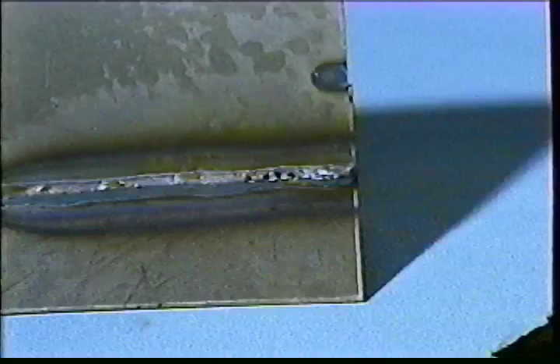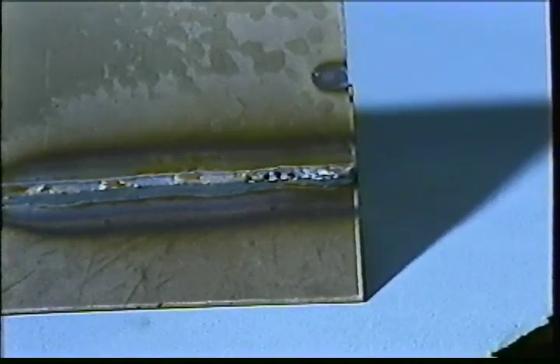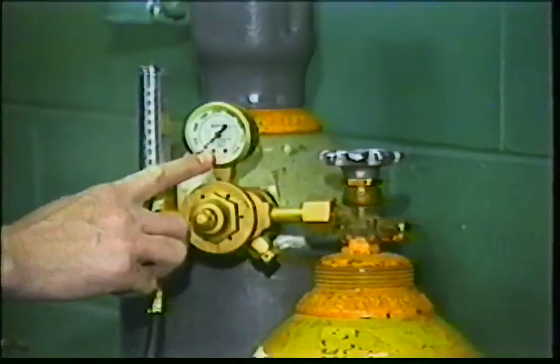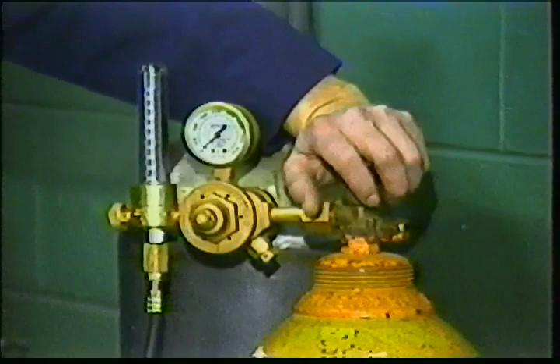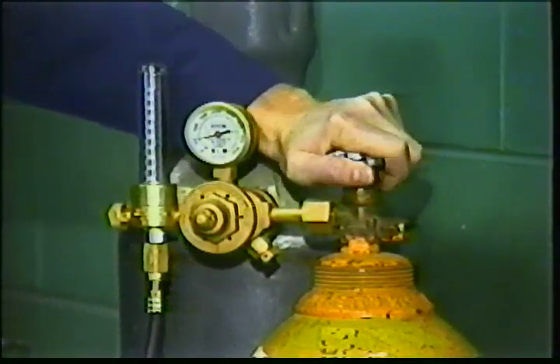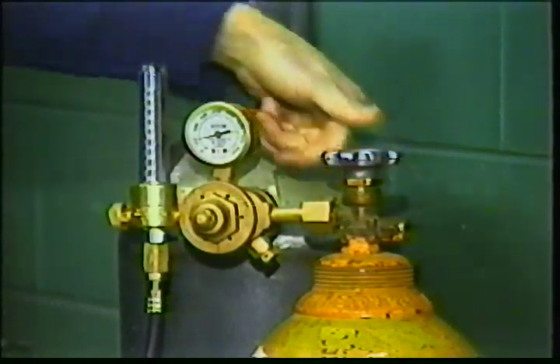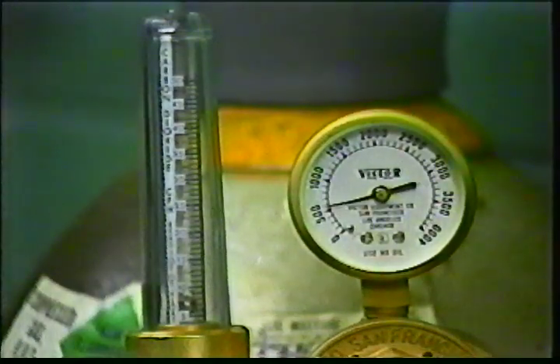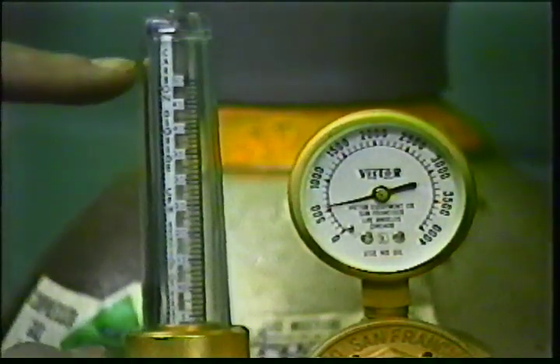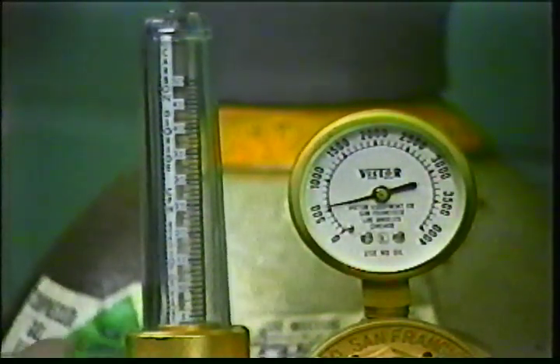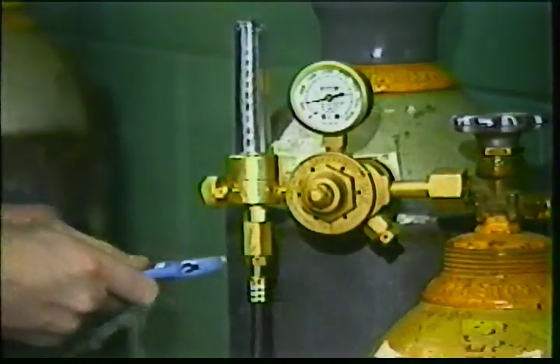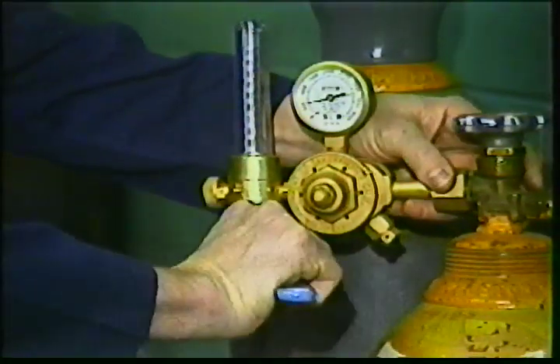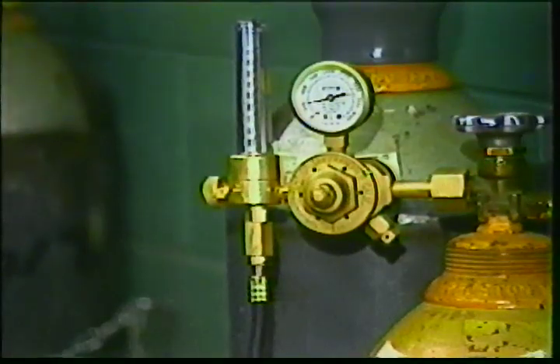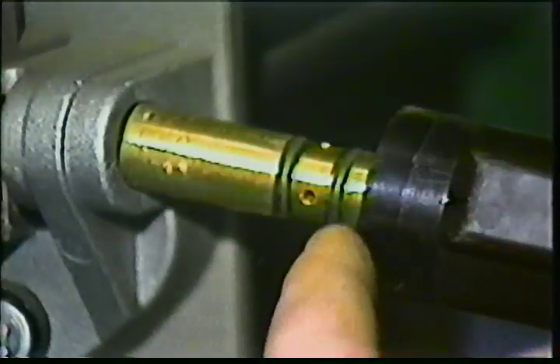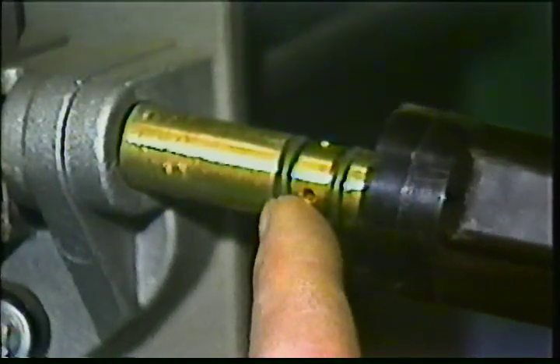Porosity is generally not caused by a faulty welding machine or wire feeder. Checking the gas distribution system in this case indicates the shielding gas was not turned on. Both insufficient and excessive shielding gas flow can cause porosity in the weld. Loose fittings or cuts in the hose can not only leak shielding gas out, but could also draw air in while welding, causing porosity. Damaged O-rings can also draw in air.